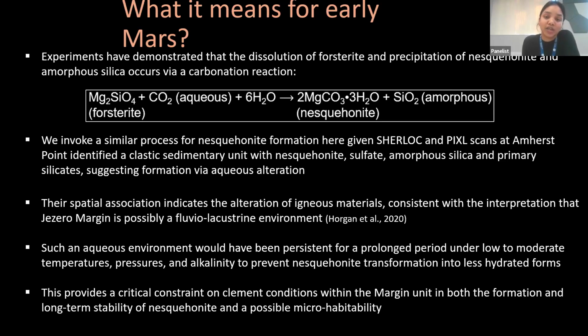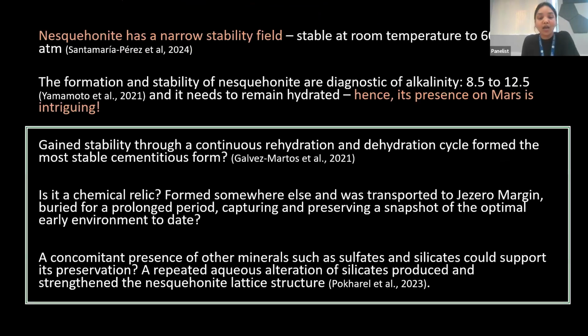Also, the spatial association of these minerals indicates alteration of igneous materials, which is consistent with the interpretation of the Jezero margin, as we've seen in papers before, as possibly a fluvio-lacustrine environment. Such an aqueous environment would have been persistent for a prolonged period of time under low to moderate temperatures, pressures, and alkalinity to prevent nesquehonite transformation into its less hydrated forms. I'm just finishing. So this also provides a critical constraint on past climate conditions within the margin unit, both the formation and long-term stability of nesquehonite, and possibly early habitability. Next slide, please.